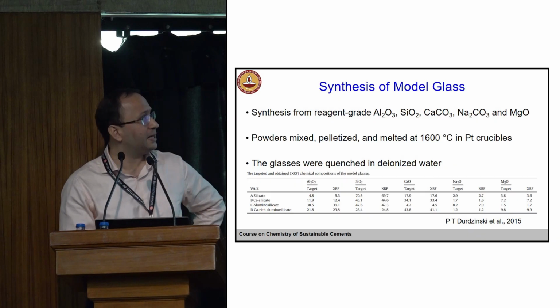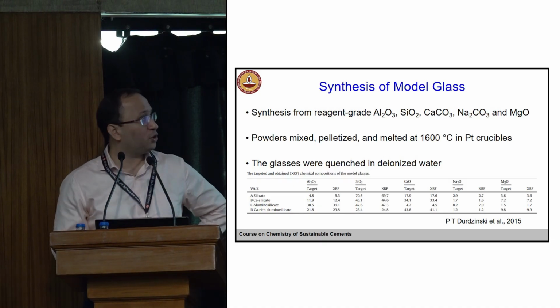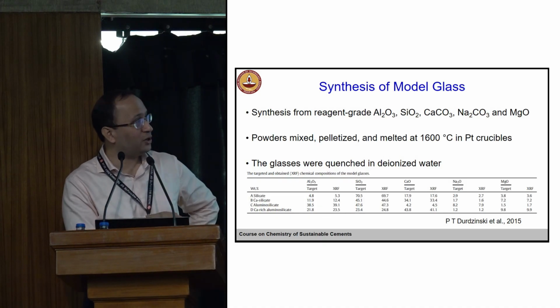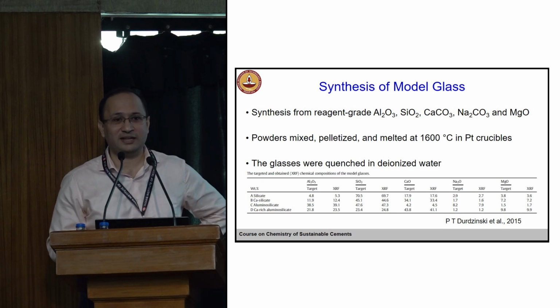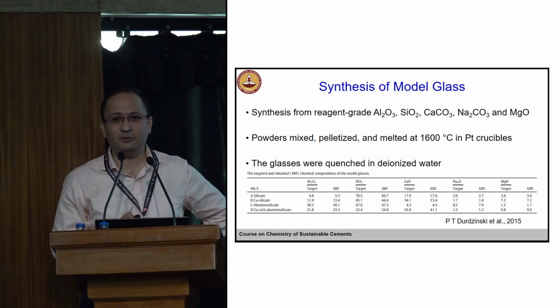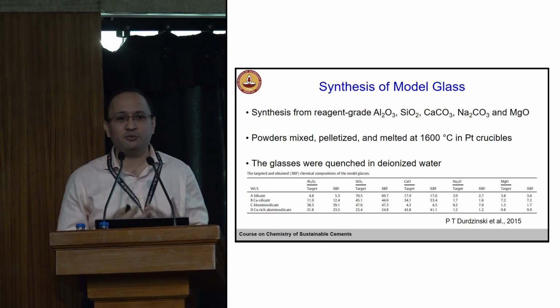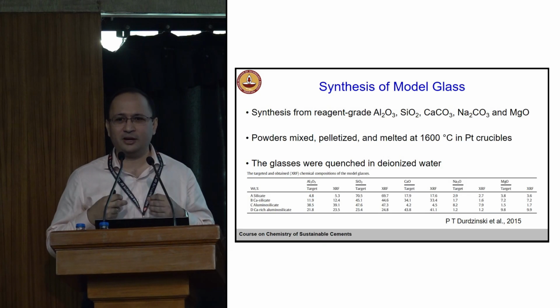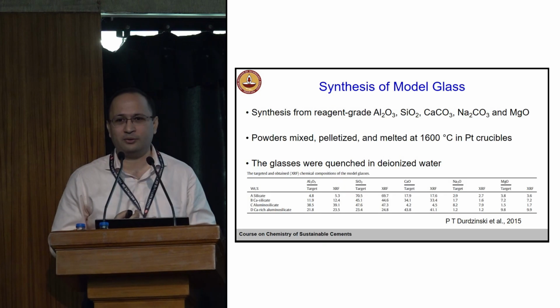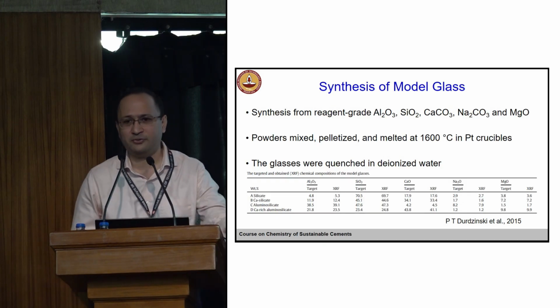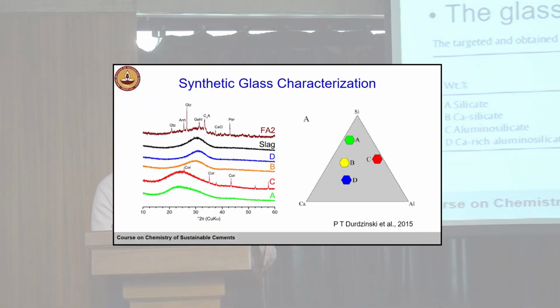Now, when we talk about the glassy phase, we have to ensure that these are cooled at a very, very fast rate. If we cool these slowly, you will form the crystalline phases. That's what we do when we make clinker also. The cooling is very, very important, so that you don't give time. If you give time, the microstructure will eventually form crystalline phases, that's the stable phase assemblage. But if you cool it very, very fast, then you will form amorphous phases. So that's what is done.